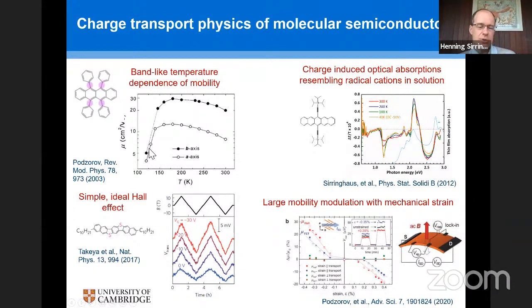This sharp drop to lower temperature is an effect of residual trapping. There are some defect states, shallow trap states, that tend to trap these carriers, but up to 200 Kelvin, you're essentially seeing the intrinsic band-like temperature dependence of the mobility, which is somewhat similar to that of silicon. It's essentially, as you cool down, there are fewer scattering events with phonons. That's how you would interpret this in silicon. So that looks a bit like band-like transport in silicon. And also, if you measure Hall effect, you can measure very clean ideal Hall effects in these systems, where the Hall resistance is inversely proportional to the carrier concentration.